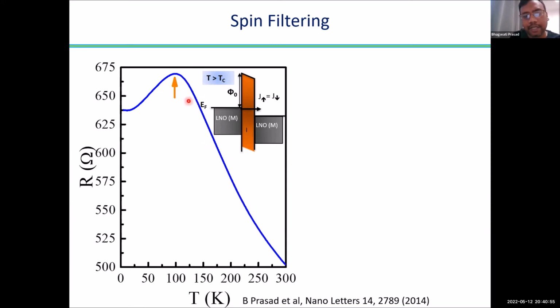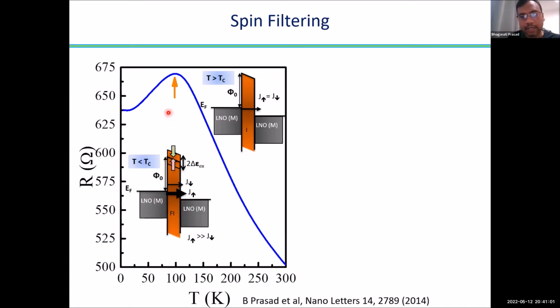Weakly with decreasing temperature. But as soon as you hit the TC, what happens is that due to the splitting of the conduction band that we discussed a few slides back, there will be different barrier heights for the two different directions of electron spin. Due to the splitting of this barrier, the barrier height for, let's say, the up-spin electron will come down. That means the up-spin electron can tunnel preferentially, more than the down-spin electron.